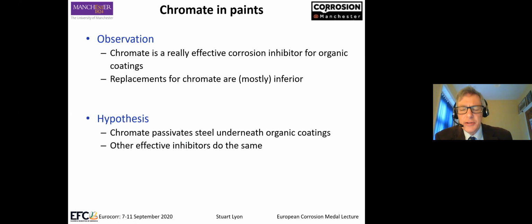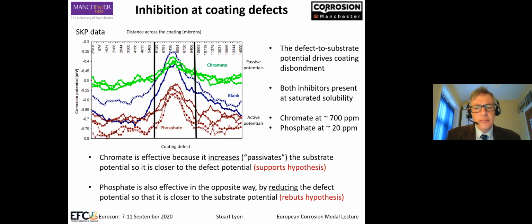If you do an electrochemical experiment, you find that chromate acts as a cathodic dominant inhibitor rather than an anodic inhibitor, because of the precipitation of chromium-3 oxide, the reduction of chromium-6 to chromium-3 at the cathode. However, we used a scanning Kelvin probe to analyze this. This is a polyester coating, which is loaded either with strontium chromate or with an alternative phosphate-based inhibitor, or is blank.